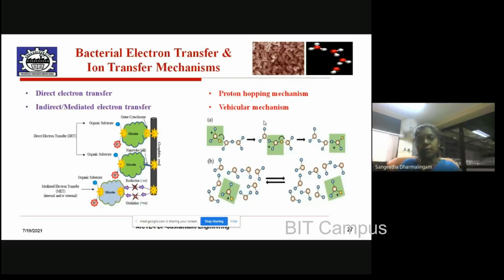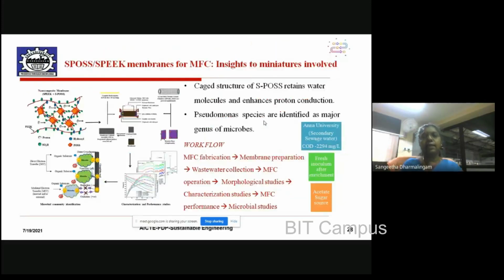Therefore, what I am trying to make you understand is that both the electron transfer and ion transfer mechanisms should be efficiently facilitated in the MFC system. When it comes to electron transfer, it is the role of the microbes. The microbes should be able to immediately transfer the electrons to the electrodes. When it comes to ion transfer, it is the performance of the membrane. The membrane should not only allow the hopping mechanism or the chemical exchange route to take place effectively, but also be hydrophilic in nature to some extent to allow the water to act as a carrier to transport the protons. If this is happening, or if you are trying to improve these conditions, you are making a better and better MFC. In that angle, we started working in our laboratory.